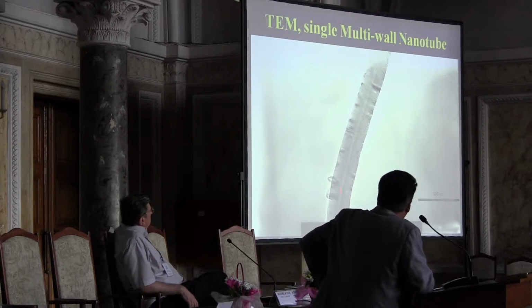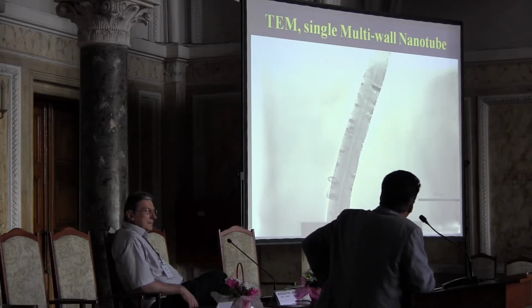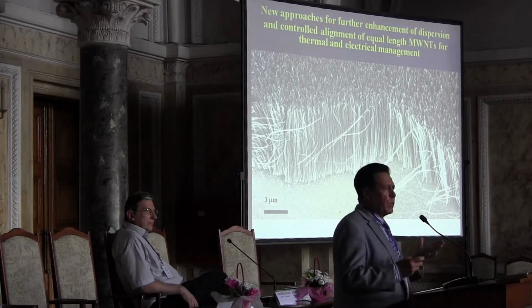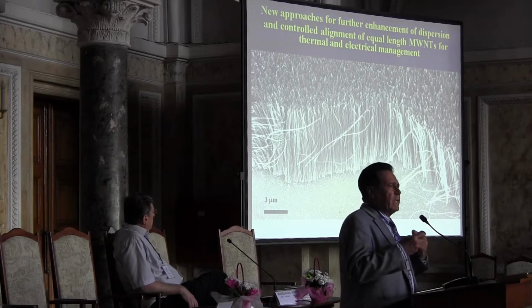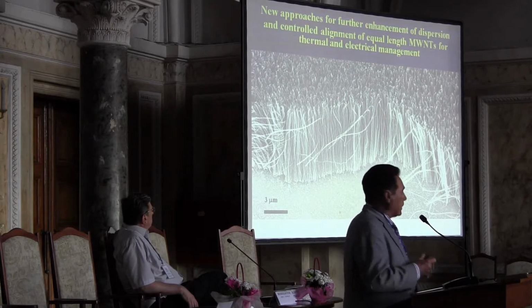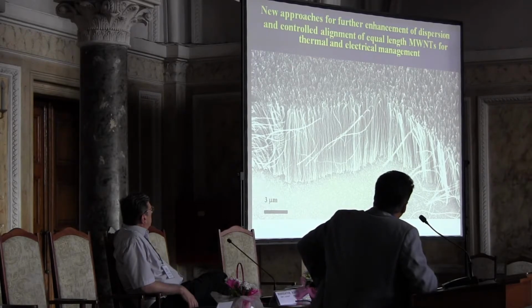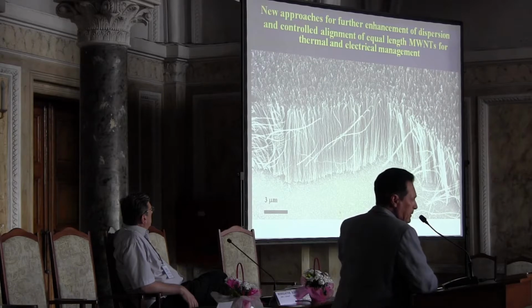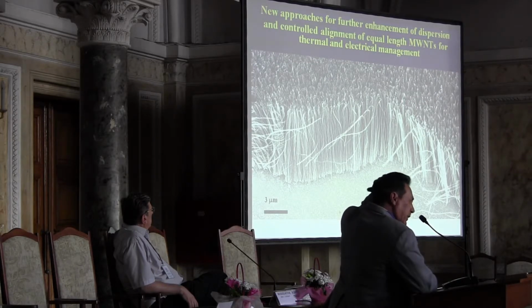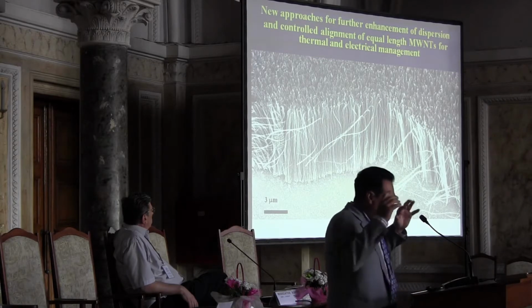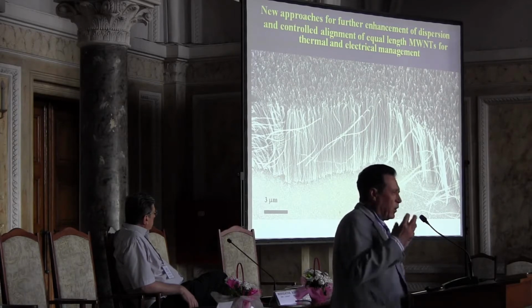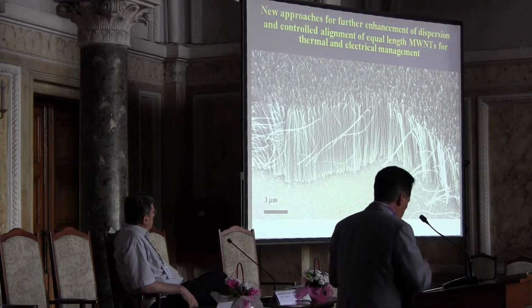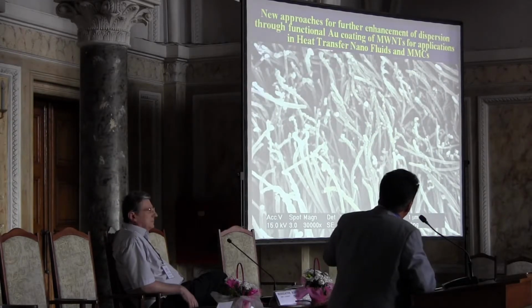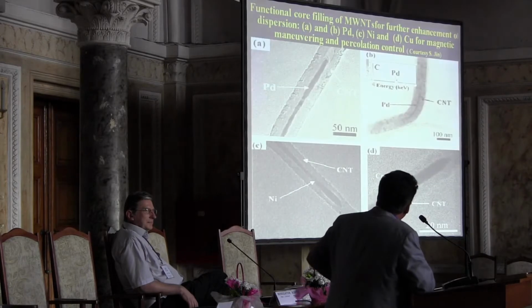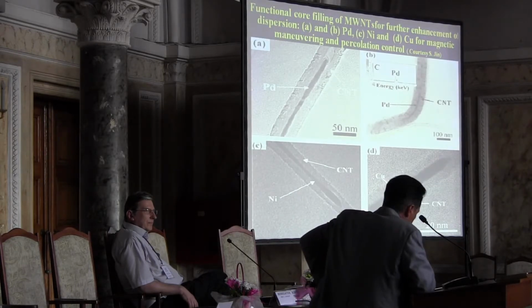So you are talking about cylindrical tubes in here, and the core of this nanotube has a very interesting property, because you can fill this core with other nanoparticles and have them help us control the nano architecture. So in this particular case with multi-walls, again, we can control the size. This is like, if you have cut your hair very short, the little hairs disperse very easily. If your hair is very long, they are clustered in agglomerates. And of course, once you separate them, you have to functionalize them, to coat them. You can, in fact, fill these with magnetic particles.